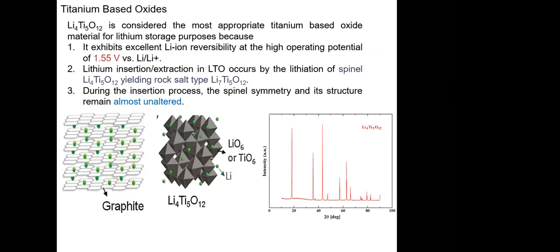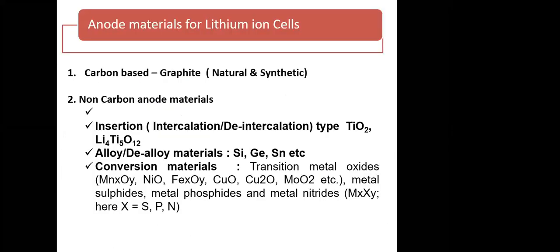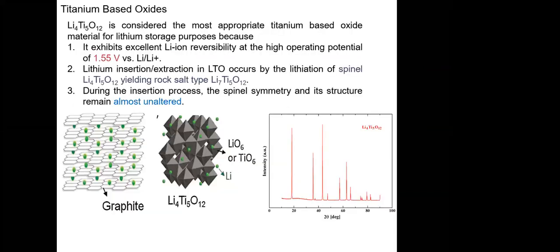Now I will focus more on lithium titanate and silicon types of materials, because these are commercialized, and right now we are also working on these two materials in our lab, trying to develop a high performance cell. Generally lithium titanate is considered the safest material, because it gives a flat plateau. This material can even be charged up to 20 C rate.